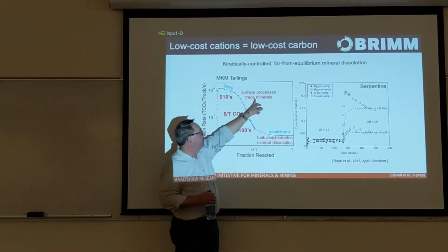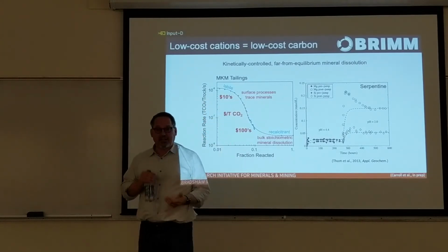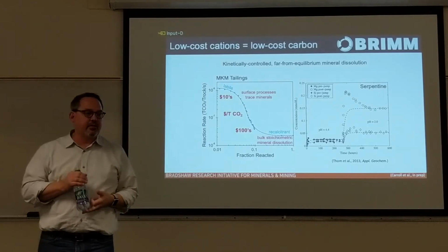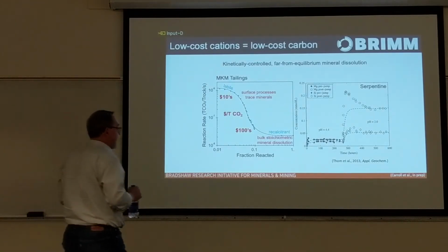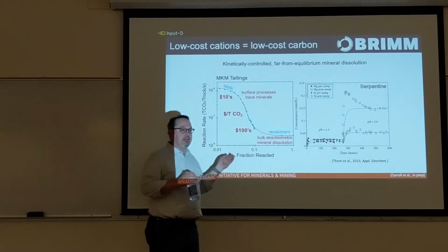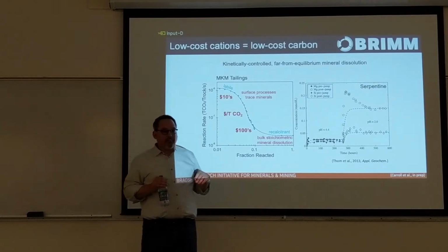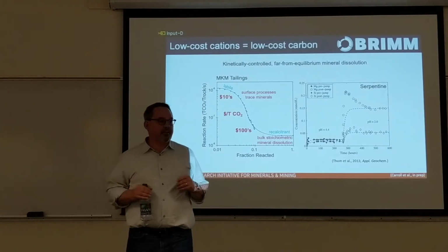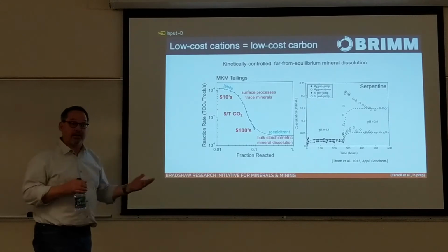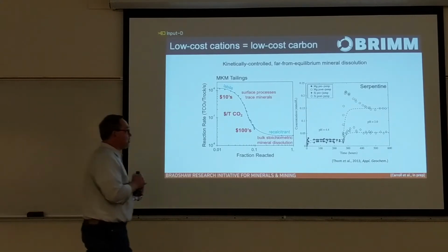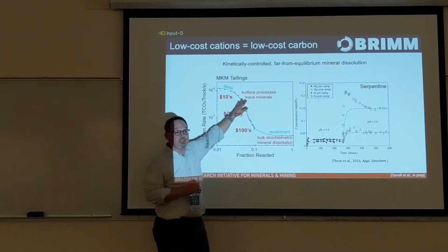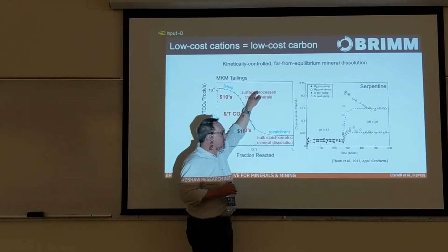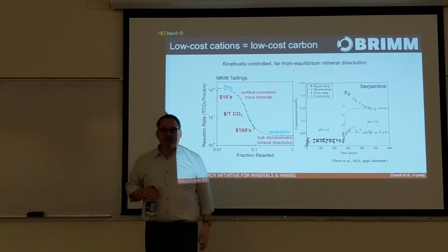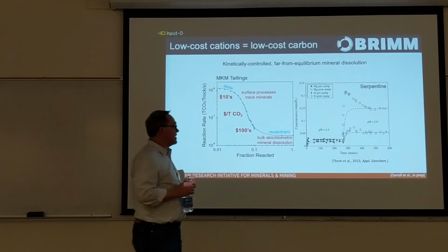It's basically controlled by trace mineral abundance. So we have things like hydrotalcites and brucite and other minerals that are inherently very fast reacting. And 2% brucite can be enough to make a mine greenhouse gas neutral, depending on the power source for the mine. So small amounts of trace minerals can make a huge impact. But in addition, we actually find that the magnesium silicate minerals have properties that release magnesium quickly as well.